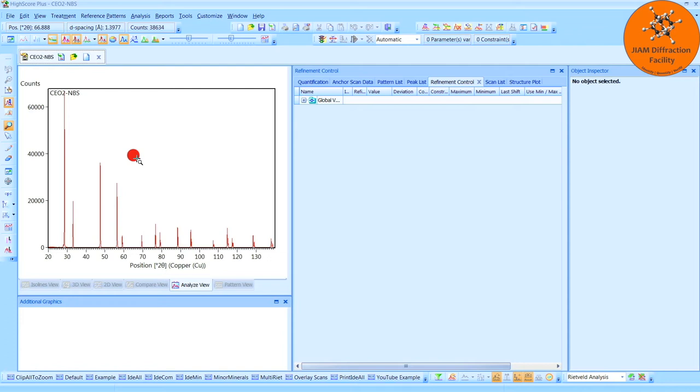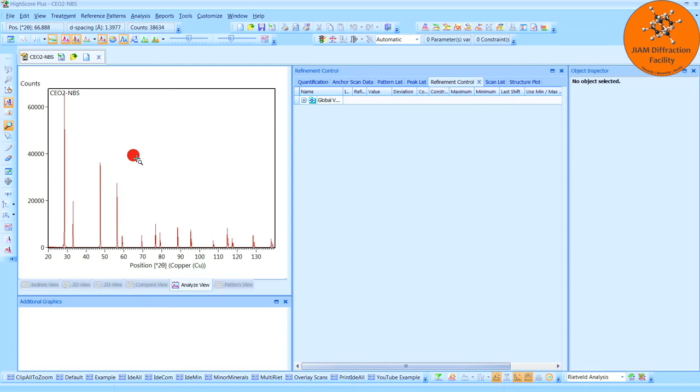One more thing I want to point out is that if you are using a single peak for your analysis, and such is the case for Scherrer's equation, you often get better results from using diffraction peaks between 30 and 50 degrees 2 theta. That's because below 30 degrees 2 theta, peak asymmetry can compromise your profile analysis, and as you increase 2 theta, your peak intensity will tend to decrease, as shown in this diffraction pattern, and smaller intensity is not beneficial for analysis either. Choosing peaks between 30 and 50 degrees 2 theta tends to give a good balance between small asymmetry and larger intensity.